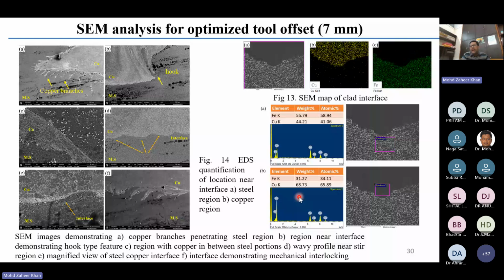Then we performed mapped EDX, as you can see in the top figures. In the mapped EDX, we tested which spots give peaks of copper. We can see that the copper peaks are only obtained from the region that is seen in the macrograph as copper, whereas iron is seen only in this region. So no iron peaks are obtained in the clad portion. That clearly indicates that iron has not been able to travel and move to the clad region.